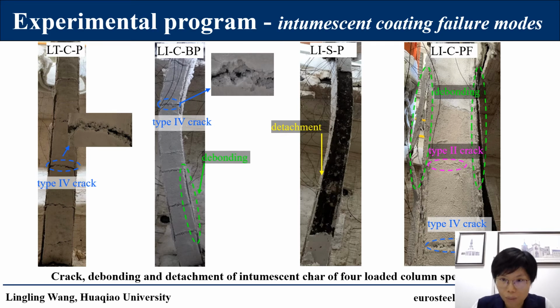For example, compared to specimens without sandblasting, sandblasted specimens had larger and more cracks but less extensive detachment, thus less debonding. During the fire test, its loaded column initially expanded and then shortened due to the rapid loss of steel strength. Column buckling occurred immediately after the shortening of the steel column.